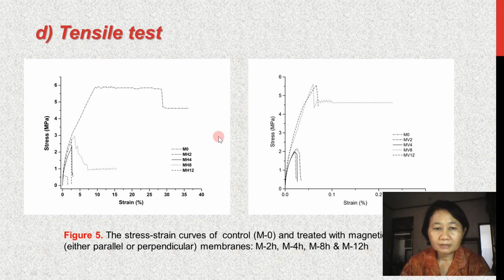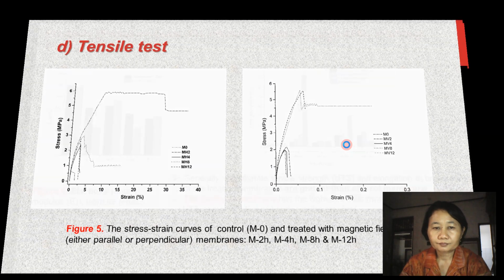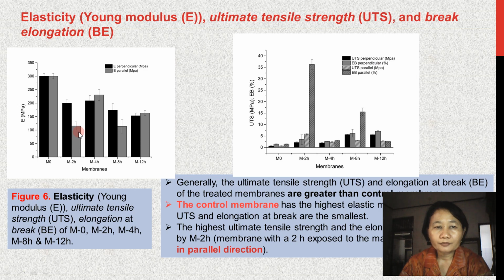We come to the tensile test. For the tensile test, this figure 5 shows the stress strain curve for control as well as for treated membranes. This is for the membranes given a parallel magnetic field direction, and then this curve shows the stress strain curve for the membranes given a perpendicular magnetic field direction. If we look at the elasticity or the Young modulus of the membranes, we can see that the Young modulus of the treated membrane is smaller compared to the control one. It means the membrane is more elastic compared to the control one.